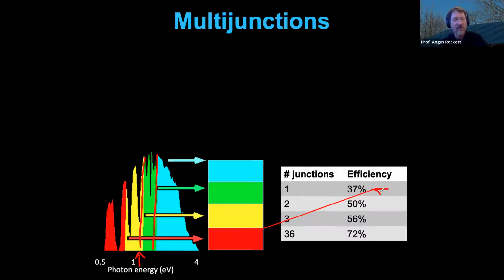And that's important because that's about where cadmium telluride is. So our current efficiency in cadmium telluride is limited, and it has a lot of opportunity to improve. We should be able to almost double the efficiency of a cadmium telluride solar cell with more research. A 2-junction cell could achieve 50% efficiency, and that's really where silicon has an opportunity. And if you went totally crazy and you had an ideal set of 36 junctions, you could get to perhaps 72%.